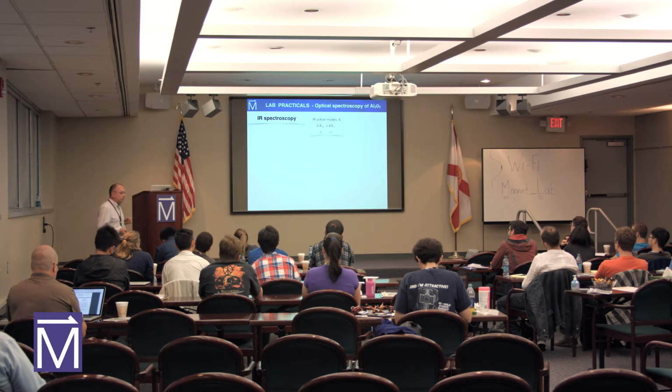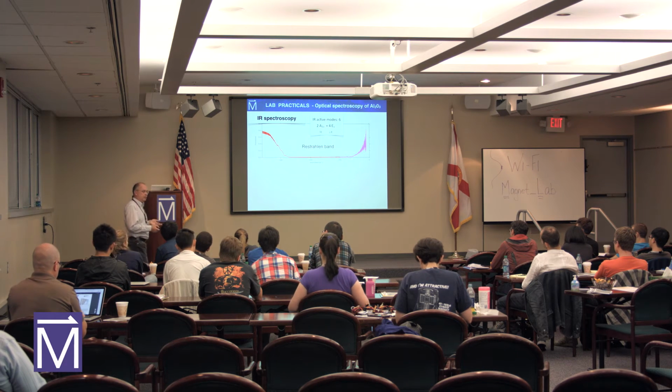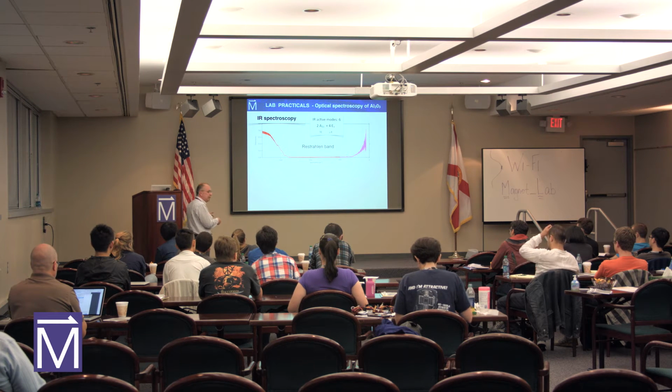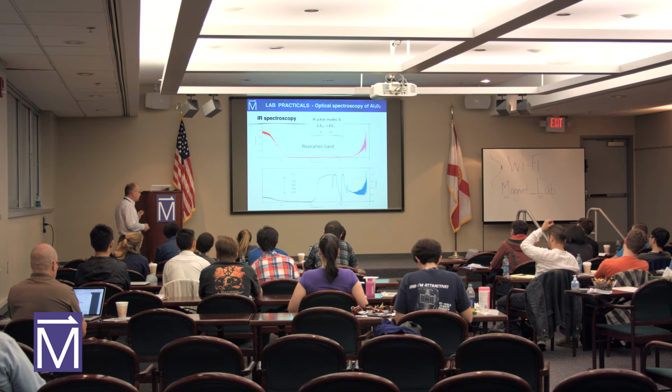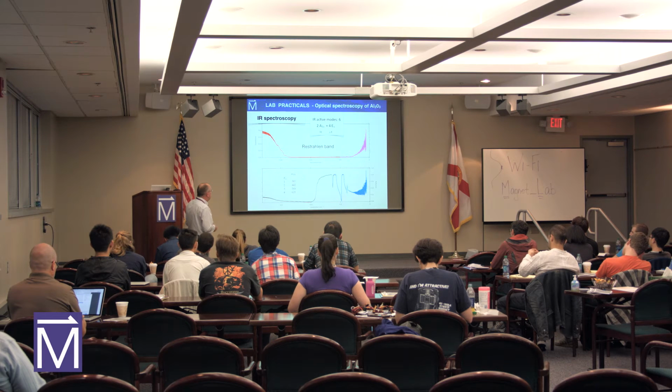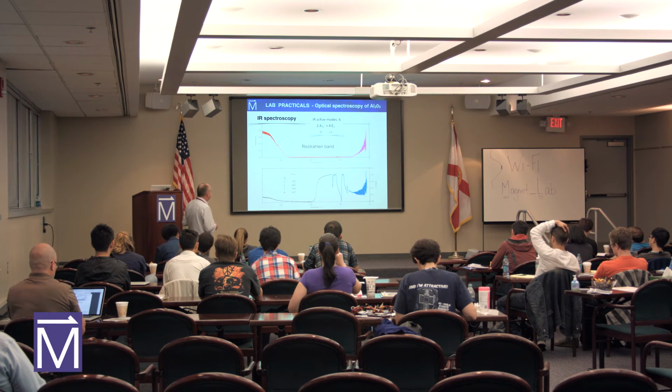What about IR modes? There are 6 of them. Simple way, let's measure transmission. We should see it, but we don't see anything. You won't see anything. It will be just what's called a Reststrahlen band, forbidden band. Nothing happening here. So the right way is to do reflectance. If you measure reflectance, you see a huge change. That's due to the phonons. And in this geometry, we measure only those perpendicular to the plane. And that's 1, 2, 3, 4.